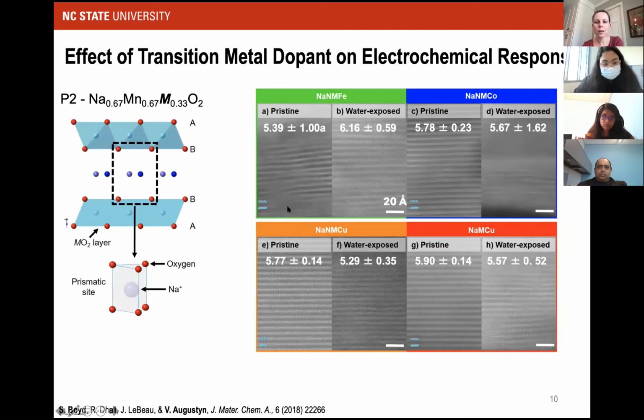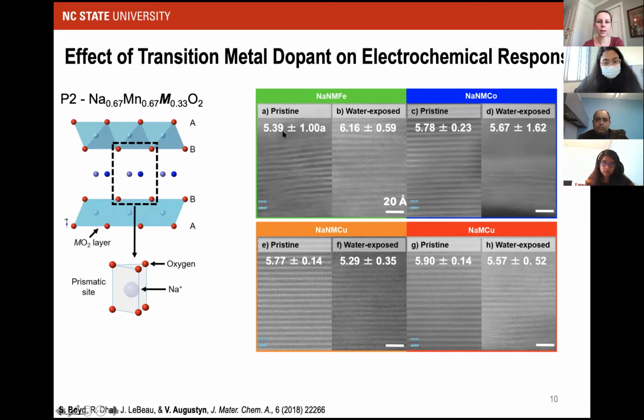Yeah. It's kind of hard to say because this is just one slice of a whole arrangement of particles, so we're looking at a very local thing. But the main thing is that after water exposure we either see an increase in the interlayer spacing or we see a significant variability in the interlayer spacing. And that we did not see in the copper containing materials. So there are kind of two possibilities. One is significant expansion, and the other is a turbostratic effect, where these layers become stacked in a disordered fashion.